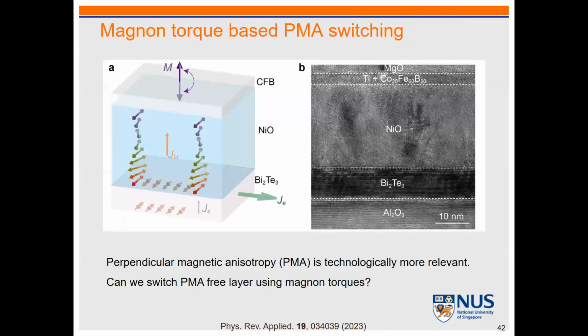Good question. So if we use YIG, some people try to switch YIG directly. So there is ambiguity, because whether my spin current will switch YIG or CoFeB, and then those magnets can also be coupled. So very complicated. If you have an antiferromagnet, it's very clear, because there is no net magnetic moment. So I'm not switching nickel oxide. My aim is to switch CoFeB, because this is the material. So this is my aim. Of course, you can study with YIG, but I think the situation will be very complex because it has magnetic moment. You will switch YIG.